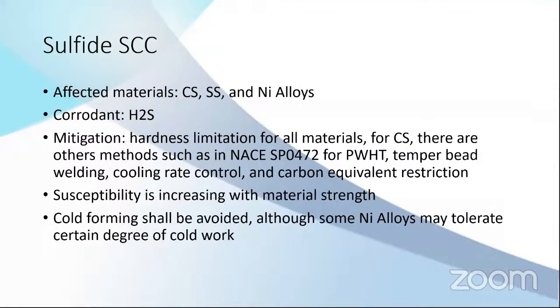And cold forming of the materials, for example bending, is not recommended and shall be avoided. Do not cold form the materials when you have this H2S service, because cold formed materials can have a very high internal stress that doesn't reflect in the hardness. So the hardness value can still be below the guidelines, but because of the very high stress inside, it can still crack. It's hard to measure the cold forming effect on crack resistance, so cold forming is almost always avoided in H2S.